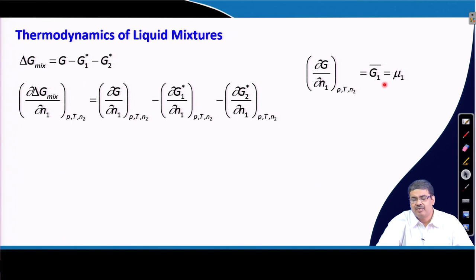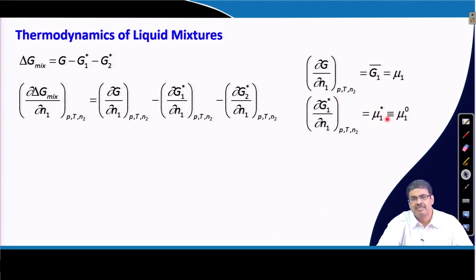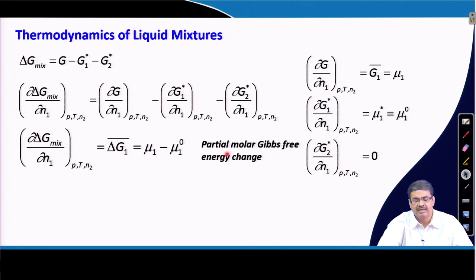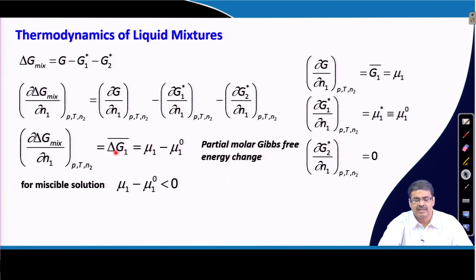We can differentiate this with the number of moles of solvent and get this expression. The partial molar Gibbs free energy is also called chemical potential of the solvent. This term is the chemical potential of the pure component and, at 1 bar pressure, this is the standard chemical potential for the solvent molecule — and obviously this term is zero. Plugging in these quantities, the right-hand side equals mu_1 minus mu_1° which is the partial molar Gibbs free energy change. For a miscible solution, we must have this quantity less than zero.